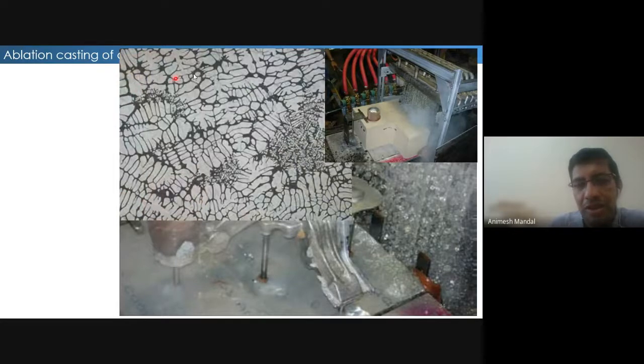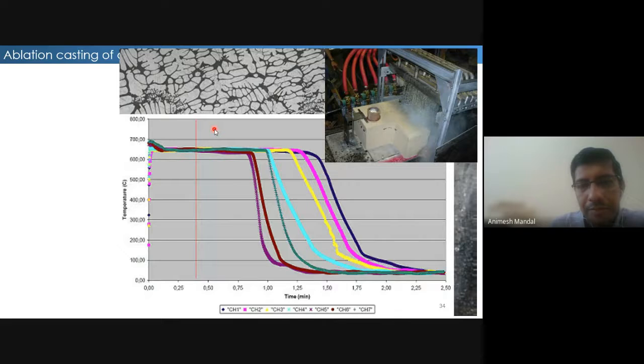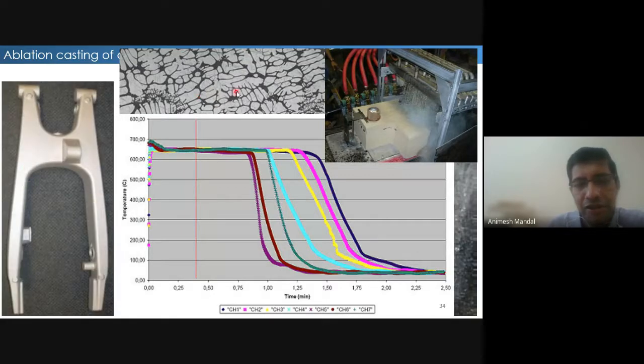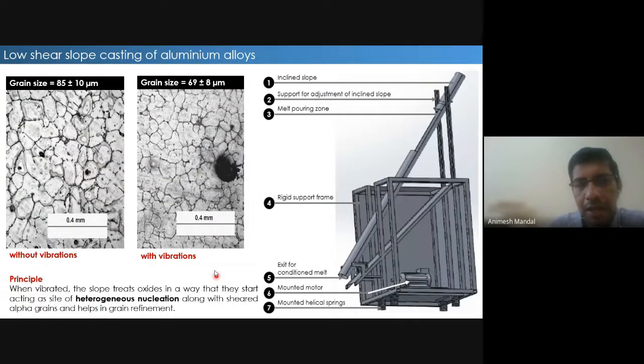You can see the microstructure is very, very fine. You are hardly able to see this eutectic silicon, which is very, very fine. The cooling rate experienced is very close to the one achieved using a metal mold. That's the beauty of this process, and as a result you are able to generate such microstructures. Even Hero Honda is already using this process to produce certain auto components.